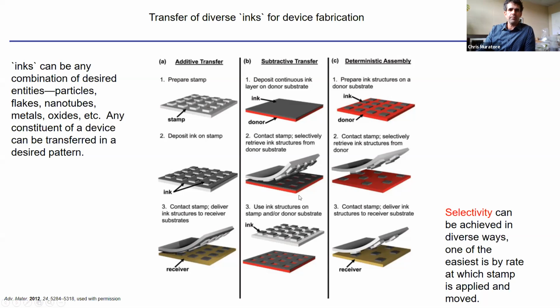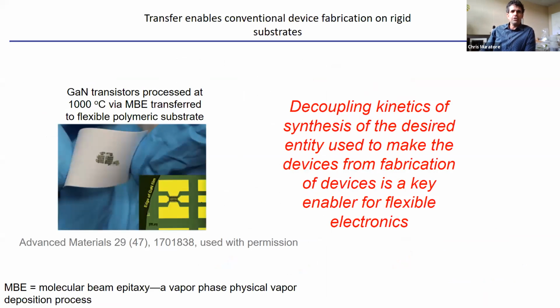For any of these transfer processes, if you've ever used an old-fashioned stamp, you've got to press it into the ink and press it onto the surface pretty hard. The magnitude of the stress that you apply and the rate at which you apply that stress have a lot to do with the performance of this transfer process. So the idea of a transfer process is very valuable because what it allows us to do is decouple the process kinetics of making the device from the limitations of the substrate.